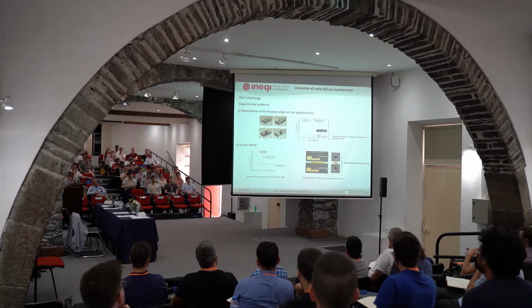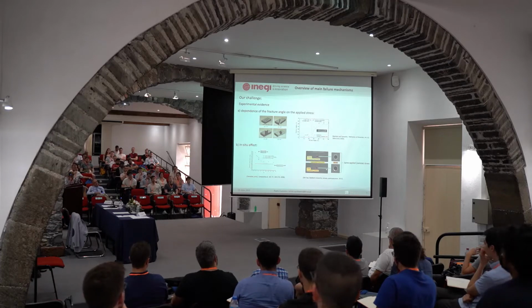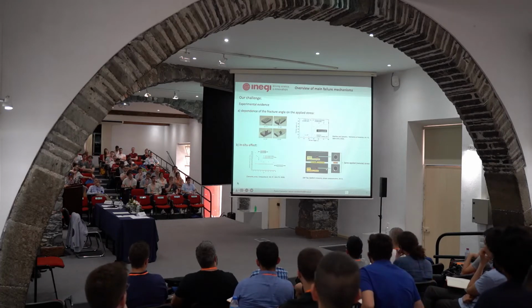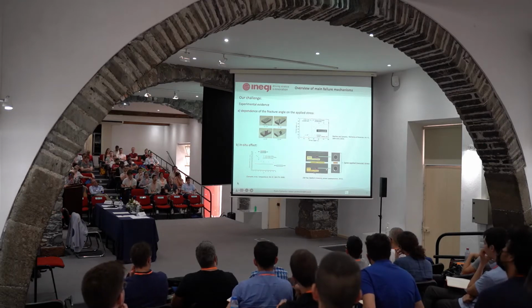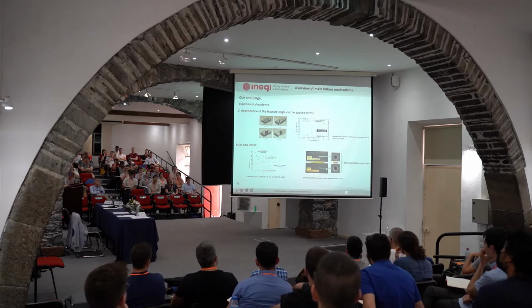So here what Steve did was to test open hole tension. So the same material, same remote stress. The difference is that this is a thick ply, so the ply thickness here is 0.20 millimeter, and here is a thin ply laminate. So the ply thickness here is 0.04 millimeter. And these are X-rays, so I'm not sure if the picture is very clear, but you can see edge delamination and transverse cracks, both from the edges and from the notch. And here, for this very same material, you don't see one single crack.